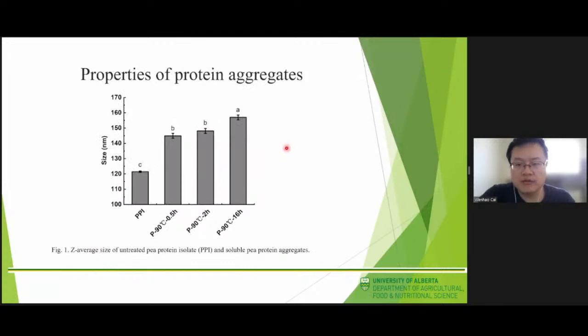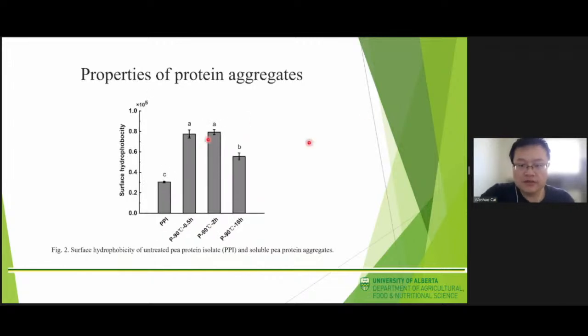Heat-induced pea protein aggregates were prepared, and here shows the average size of untreated pea protein isolates and the soluble pea protein aggregates. The size increased with heating treatment time, and all of the pea protein aggregates had larger size than native pea protein, so it can also correspond with the TEM results. The surface hydrophobicity of pea protein aggregates was also tested.